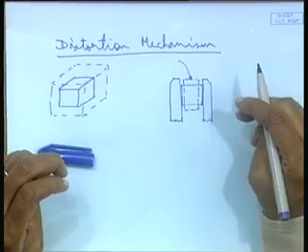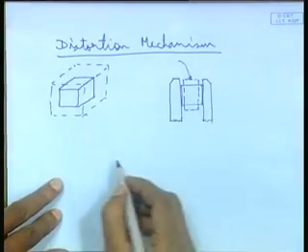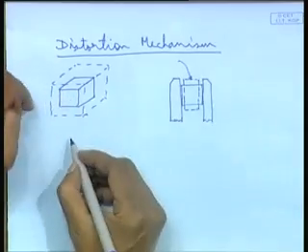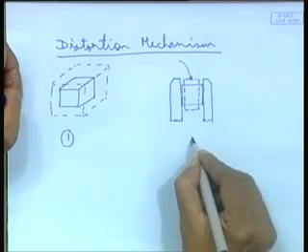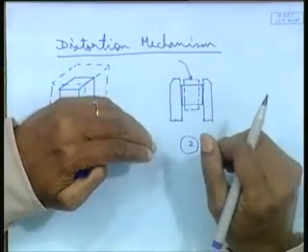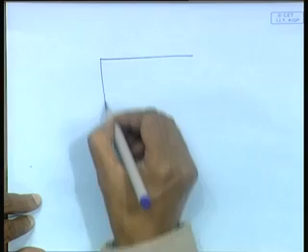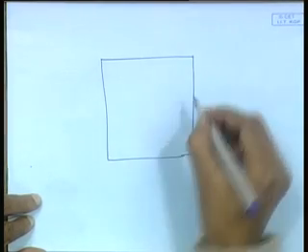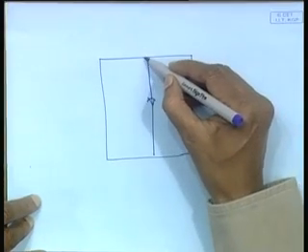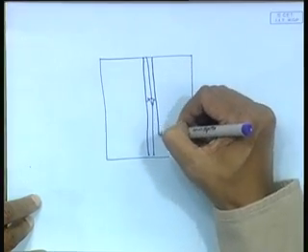Why? That means the dimensions have changed. What has happened is that when I was heating it, the expansion and contraction was not uniform. In the first case, the expansion and contraction was uniform, meaning in all directions it could expand freely and again contract freely, but here it could not expand. So the stresses developed and the eventual result is this. This concept, equated to this, will give you why deformation takes place because of welding. Say two plates being welded means what? A zone along the weld line, say this is my fusion zone.